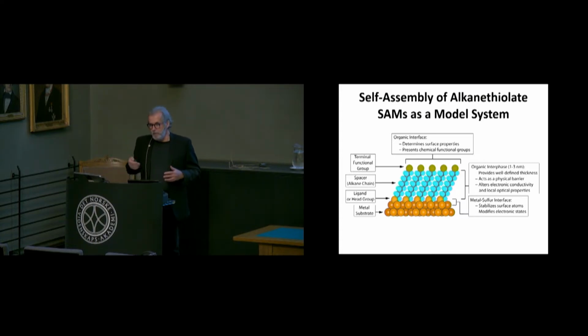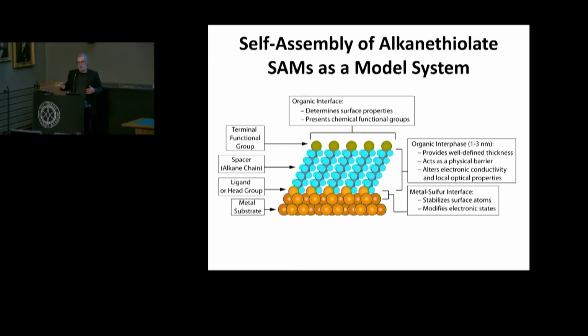And if those characteristic functional groups have orthogonality in terms of how they bind at various interfaces, you can arbitrarily organize. And that's where the word self-assembly comes in, because it's driven by the characteristic balance of all the molecular interactions that are present: the pairwise interactions of nearest neighbors, the characteristic metal substrate bonding interactions, and the interactions with whatever is the contacting ambient phase expressed at the organic interface of this material. And out of that comes a characteristic structure.